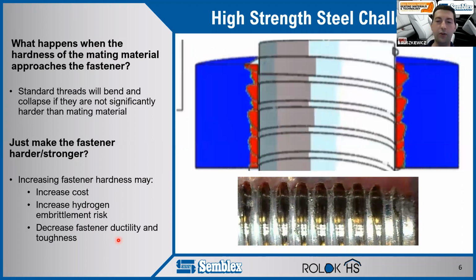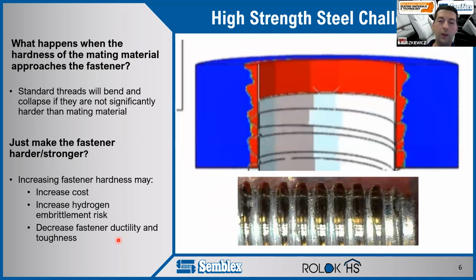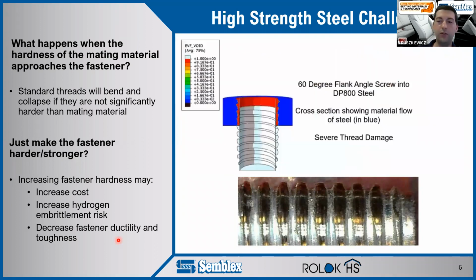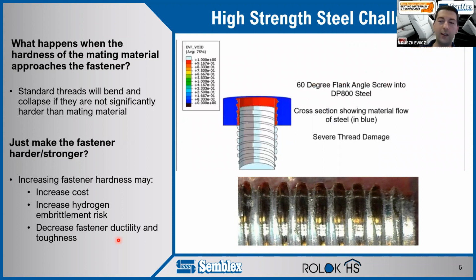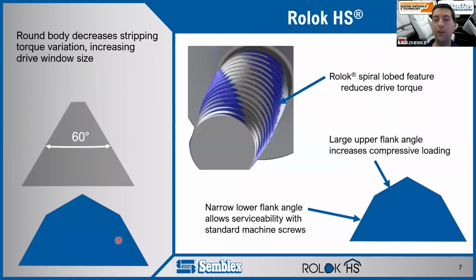So if we want to make a fastener that can go into these high strength steels, but we don't want to change the heat treatment, what do we do? Well, if you remember, I said most traditional thread rolling fasteners had a 60-degree thread flank. So maybe that's the problem, and that's what we looked at when we developed Rolok HS. On the left side of the screen, you can see a depiction of a traditional thread rolling fastener's flank, which, as mentioned, is 60 degrees. Below that, we see Rolok HS.